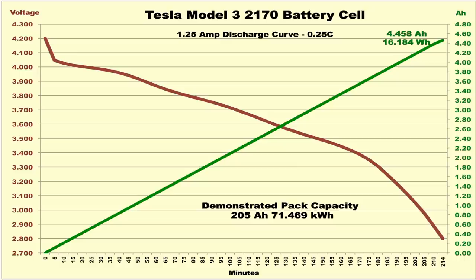And in fact, let's see, what did the watt-hours. Watt-hours I actually calculated at each. We were at a steady 1.25 amps, but the voltage, of course, changed across the curve. So I actually did the watt-hours every 5 minutes and sort of summed them. And that's probably the most accurate way to do it. 16.184 watt hours per cell.